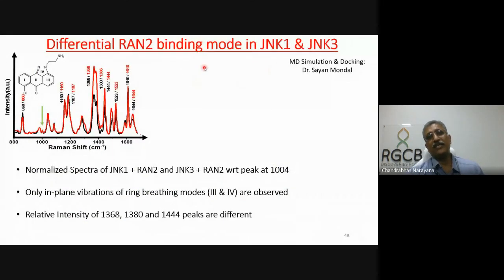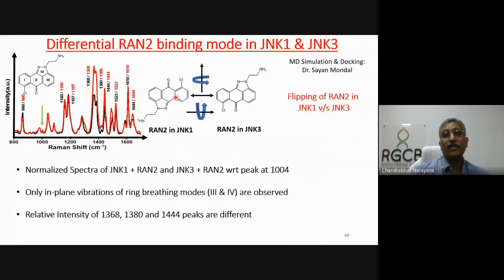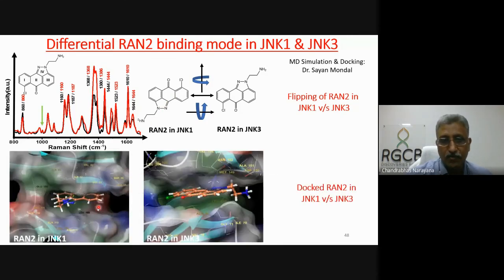Now, to show you that it binds differently in JNK1 and JNK3, the RAN2 molecule is this. You can see the Raman spectra are more or less similar, but there is a very subtle variation in the intensity of these two peaks. What does it mean? It is because this particular molecule is flipped, and that flipping gives you this change in intensity. If you look at the molecular modeling, you also see that the NH2 is facing towards you in JNK1, while the NH2 is facing inwards in the case of JNK3. So though this pocket is very similar, the interactions with the protein are quite different, making this molecule sit differently. So you can not only look at the screening, but also tell that the homology model is working very well. It can be a very good tool to verify binding of the molecules also.